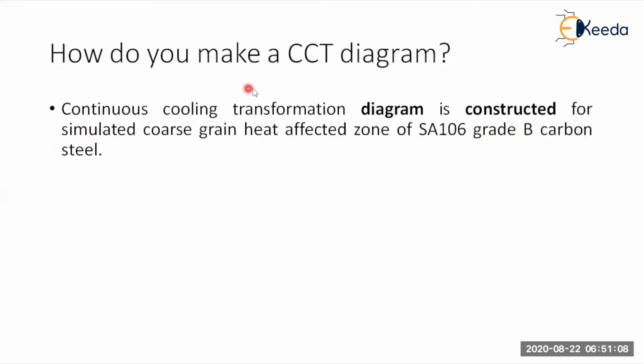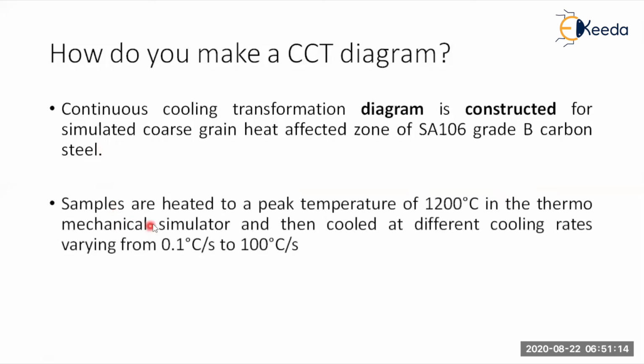All this data you have to note down, and whatever samples are taken here, you have to heat those samples first. Before taking the data, you have to heat the sample. Suppose you take a peak temperature of 1200 degrees centigrade in a thermomechanical simulator. You can use any other good simulator, but the thermomechanical simulator is the best. After it reaches 1200 degrees centigrade, then you have to cool it.